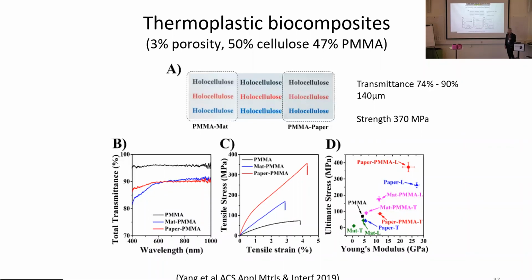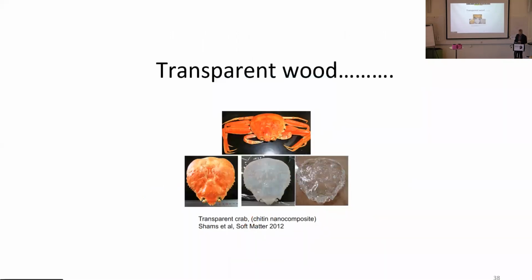It's a combination of several things, but one is that the intrinsic properties of the fibers are much better because we preserve them to a better extent. And the other thing is that we really know how to use the polymer now, because we have done all these careful experiments, so we make sure that the polymer is really impregnated at a very fine scale. I'll finish off with transparent wood, which is a recent project.